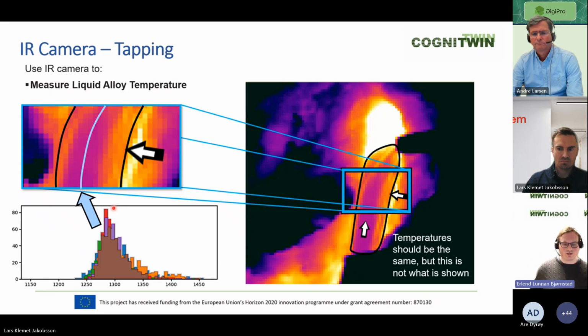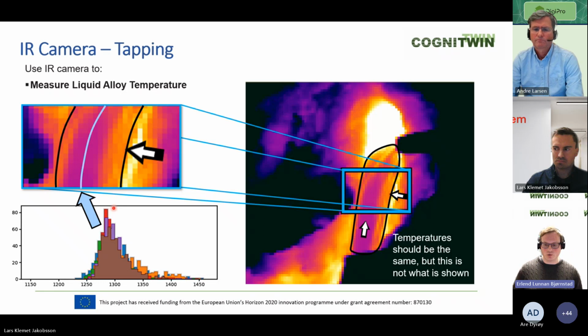So one of the things we wanted to see is if we could measure the temperature from the tapping jet using this IR camera. One of our issues here that you can see is that the temperature over the whole tapping jet is not consistent. So you can't just naively point a camera at the jet and get out a reasonable temperature. And the tapping jet's shape and size will also change depending on the conditions of the furnace.